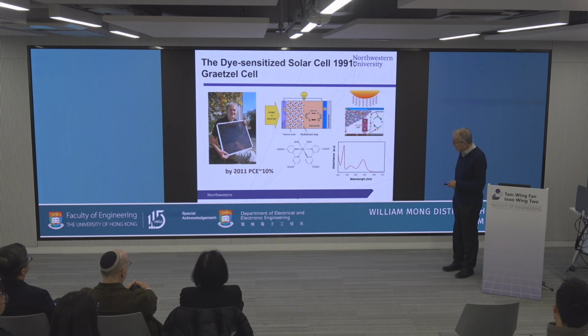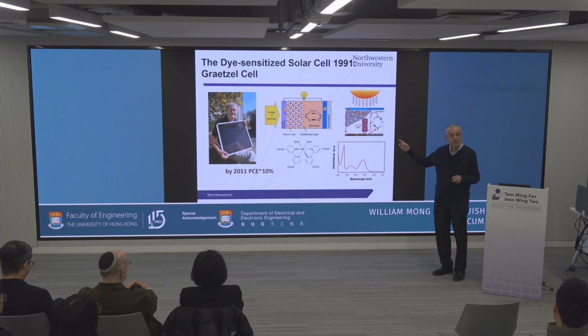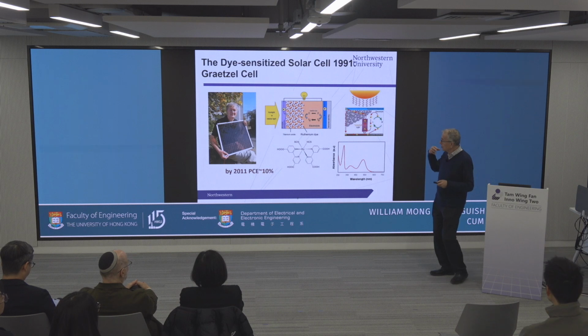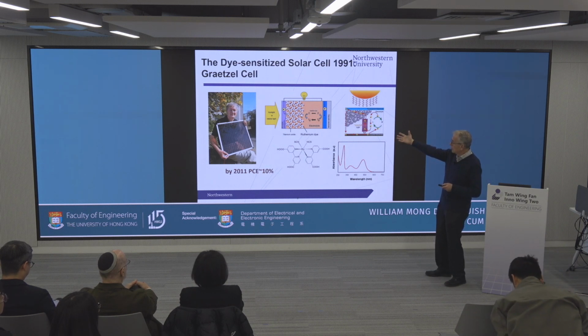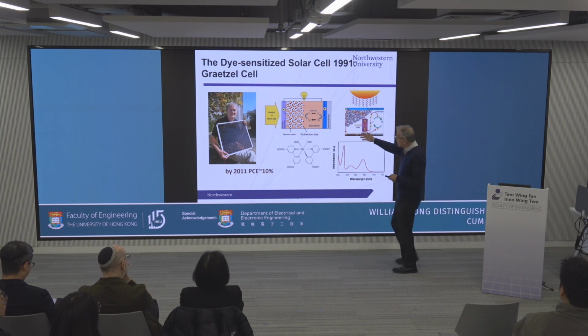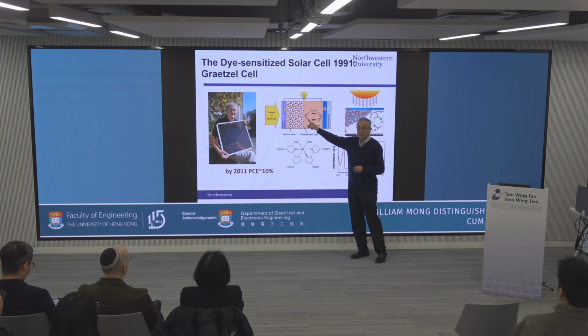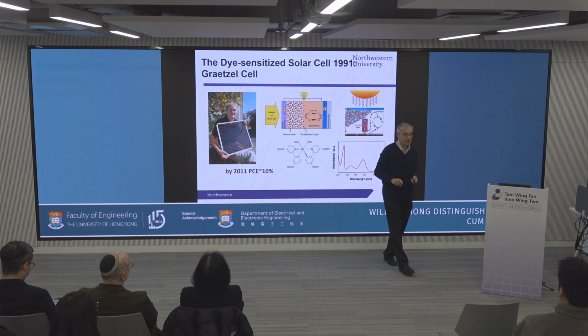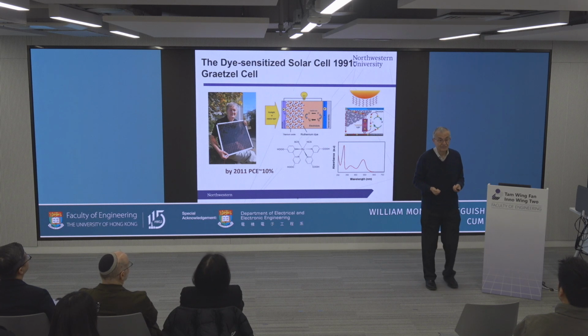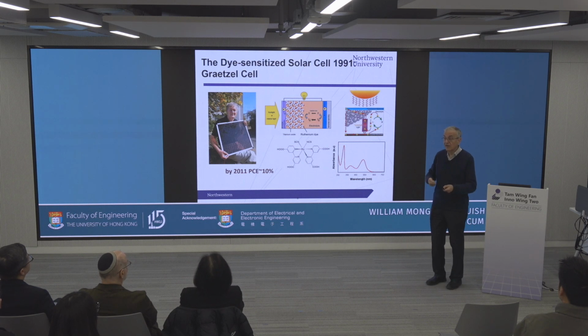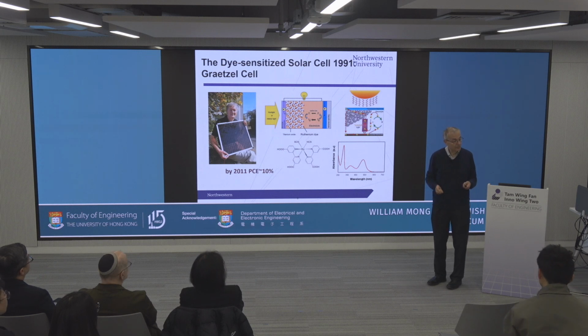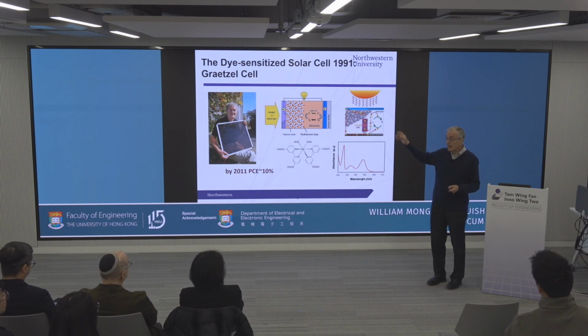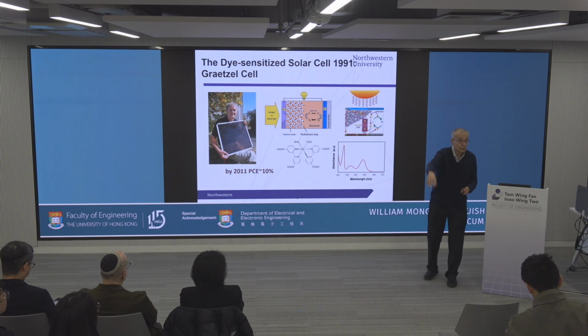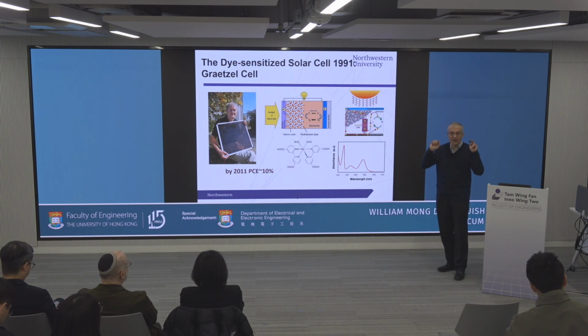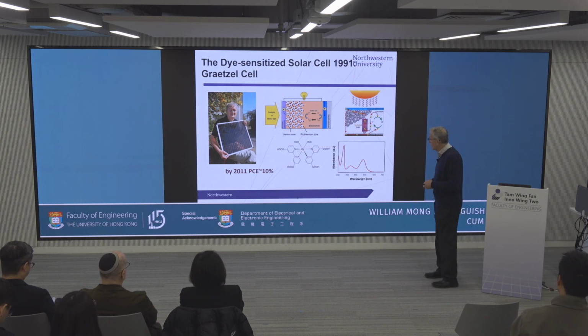So by 2011, everyone was struggling and thinking very hard to make this a solid-state device. And so the most logical approach when you look at this, you say, okay, all I have to do is maybe keep this because this is doing the work, but replace the solvent with something, maybe a polymer that can dissolve an iodide salt, make an ionic polymer, it would be conducting and do the same job. That's what they were doing. It was, and this efficiency was dropping down to 1%, 2%. So it kind of like almost working, but it wasn't competing at all.